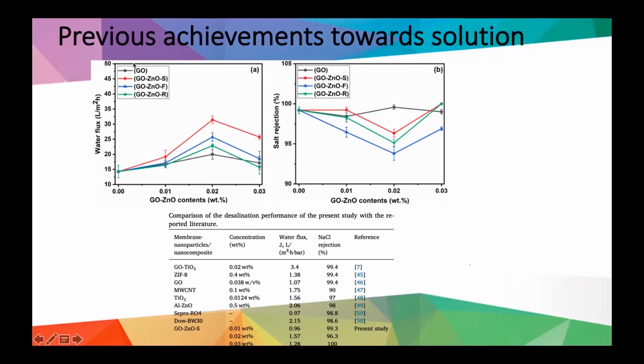We can see here the membranes containing only graphene oxide in black, and the other colored ones having the same concentration of graphene oxide and zinc oxide, but with a change in the morphology of the zinc oxide nanostructure between spheres, flowers, and rods. The zinc oxide spheres, found in red, were the best for water flux. And when we go through the percentage rejection, you can see the blue one, which is the structure with the flowers.